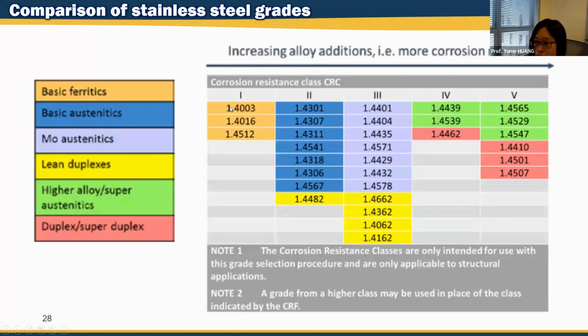Okay, so if we look at the corrosion resistance in different classes, the higher classes offer the best corrosion resistance. You can see that the duplex or super duplex is here. Also the Stonecutters Bridge, the duplex 1.4462 is not the highest grade, but it is the fourth grade. It actually has the highest corrosion resistance compared with the other commonly used stainless steel. So we can see why the Stonecutters Bridge wanted to pay more for the high-cost duplex, because it does have a high corrosion resistance.